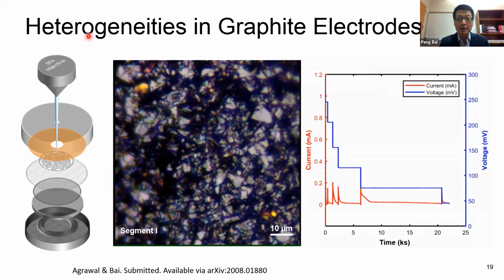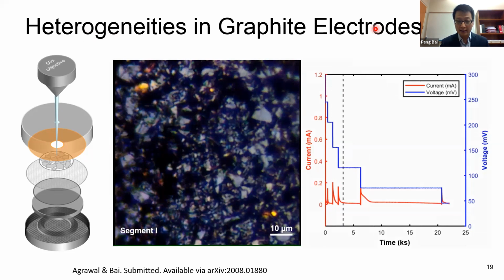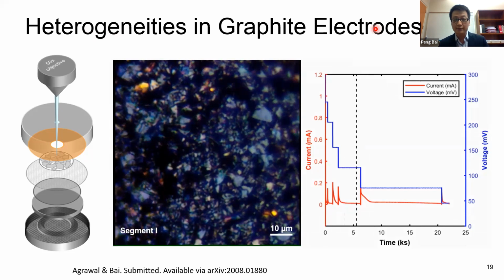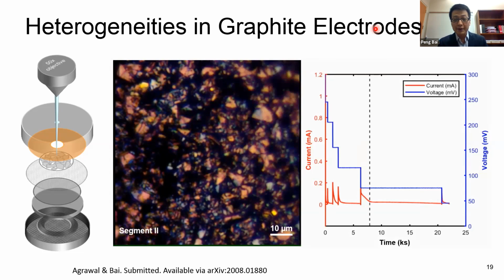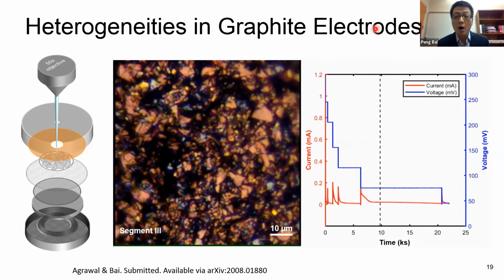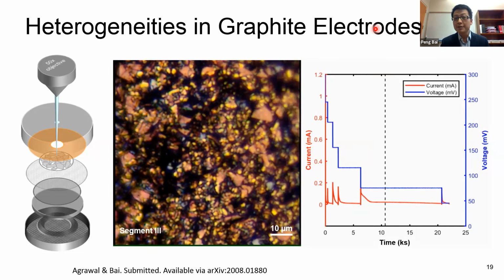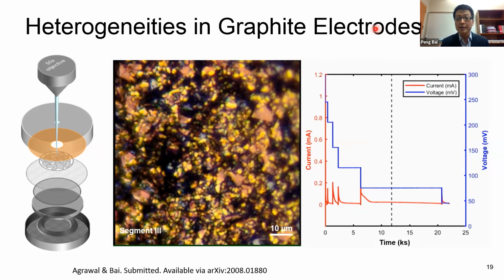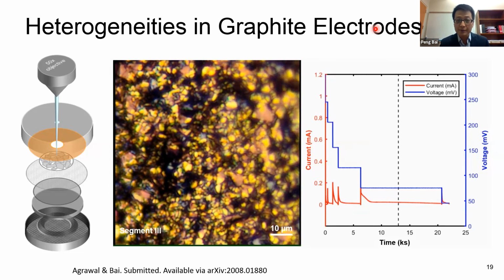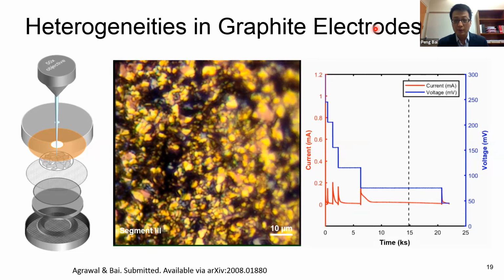So you can see here, we're doing a so-called PITT experiment, potentiostatic intermittent titration technique, PITT. Simply speaking, it's just a series of voltage steps. So you can see here, initially the black particle turned blue. Then now, to the final step, you can see here, it turned red. And while we are holding the voltage there, it further turns gold. So there is actually phase transformation, from blue to red, from red to gold, when lithium goes into the graphite particle.